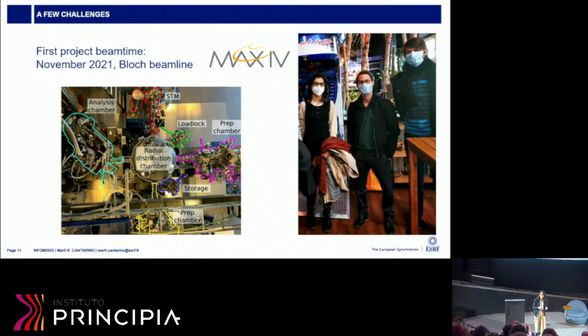So I was already in the third year of my PhD doing this kind of experiment, but luckily we had a lot of expertise with the same detector, because they have exactly the same one in the beamline there. So we had a very profitable beam time. In 6 days, we measured 7 samples at 2 different temperatures for most of them. So it was very good, and I got basically all the results of my thesis in that one week.